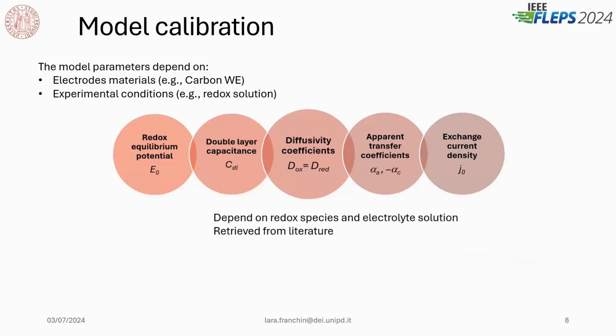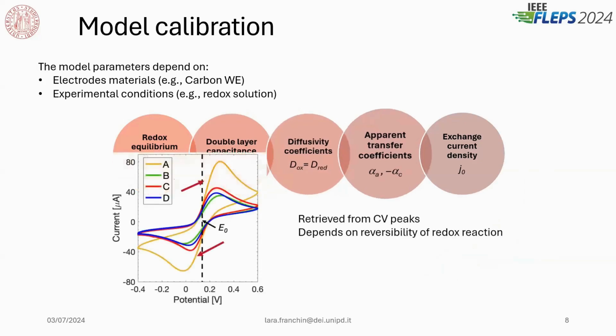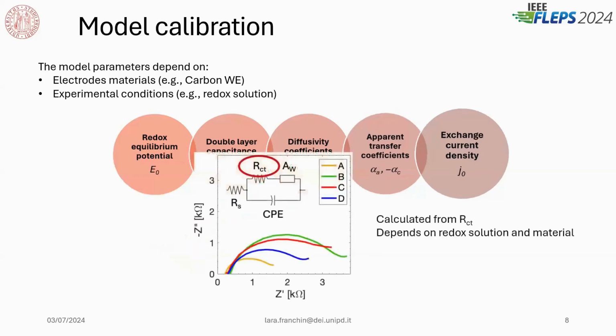The double layer capacitance is dependent on the electrolyte and the area, and to avoid this dependency, we actually normalize the value. Then the diffusivity coefficients are dependent on the redox species of the electrolyte solution, of course, and they are retrieved from literature. And then the apparent transfer coefficient is an indicator of how reversible the redox reaction is. Meanwhile, the last one is the exchange current density, which is calculated from the charge transfer resistance, and it's dependent on the redox solution and the material that we used on the electrode.